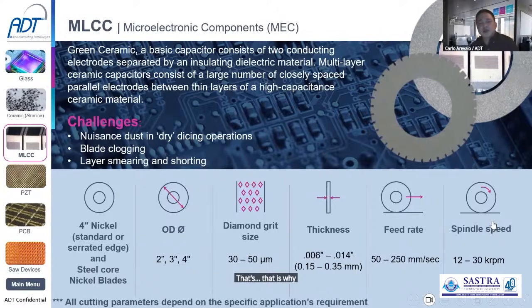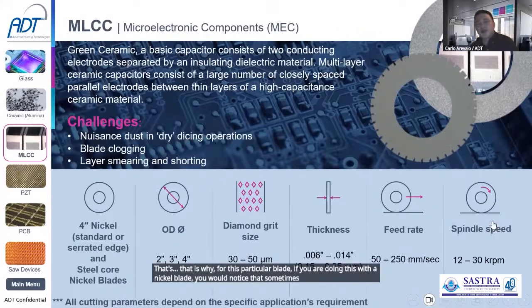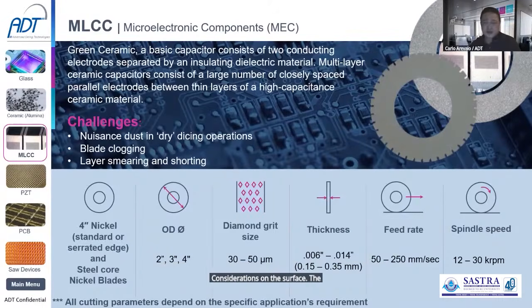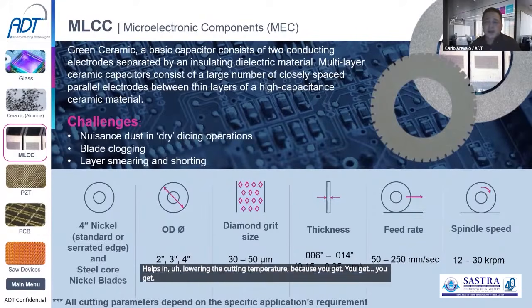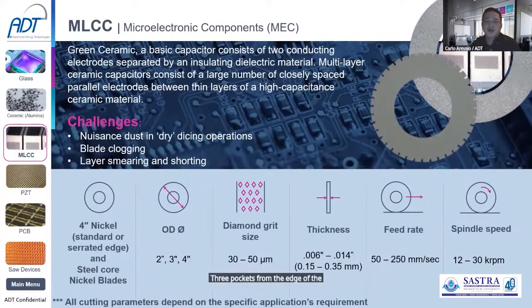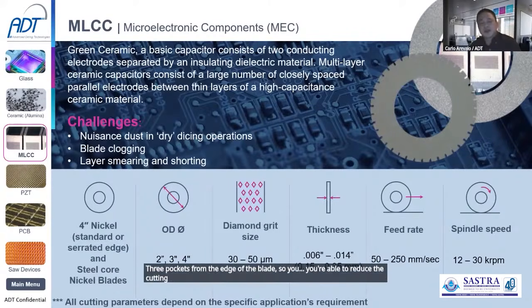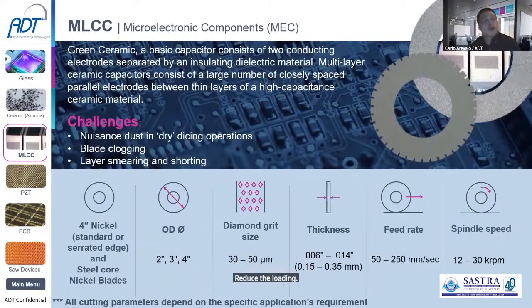That is why for this particular blade, if you're doing this with a nickel blade, you would notice that sometimes the recommendation is to have serrations. If you look at the right photo here, you would see that this blade has serrations on the surface. The serrations help to reduce blade loading and help in lowering the cutting temperature because you get free pockets from the edge of the blade. So you're able to reduce the cutting temperature and reduce the loading to a level that helps eliminate the blade loading or clogging.